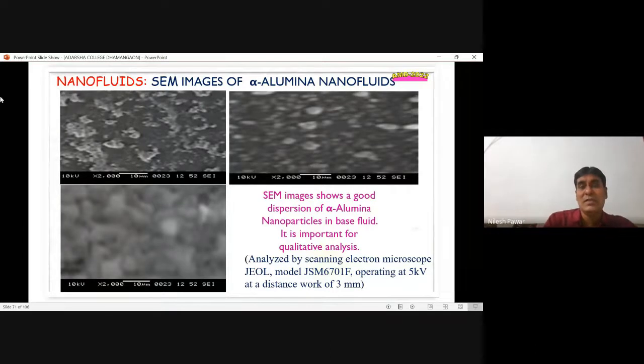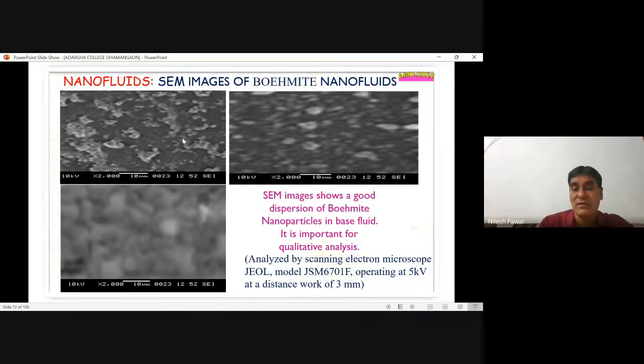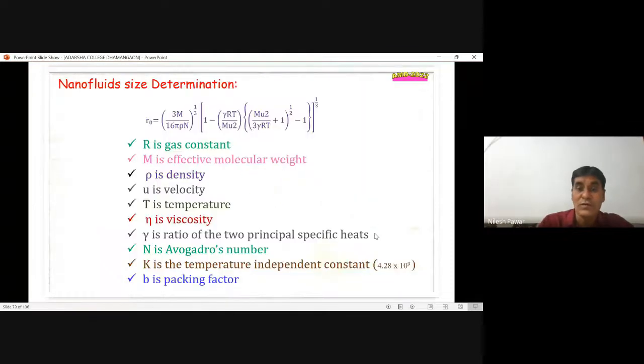Now, these images are completely different from the images of the alpha alumina nanoparticle, and hence we conclude that the nanofluid is excellent for the study. What here? The images show the good dispersion of Boehmite nanoparticles in the base fluid. It is important for the qualitative analysis. These are also the images of alpha alumina, and these are the images of the Boehmite nanofluid.